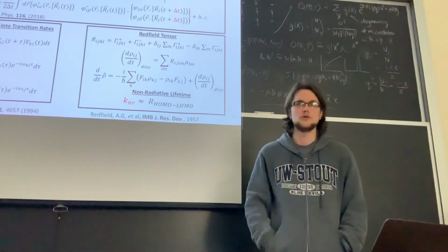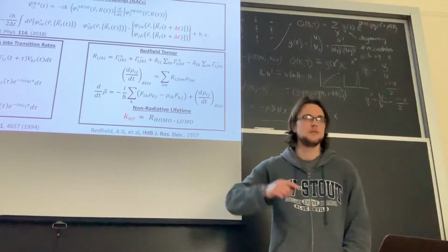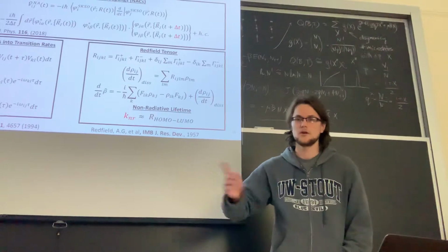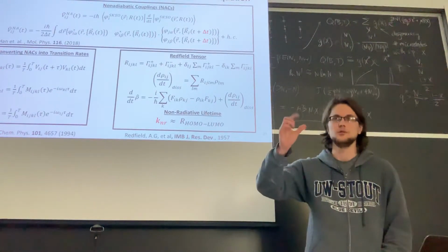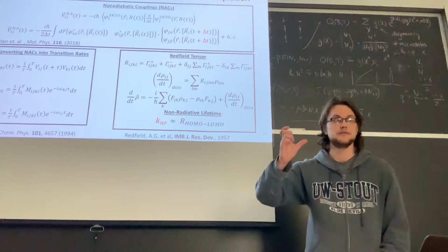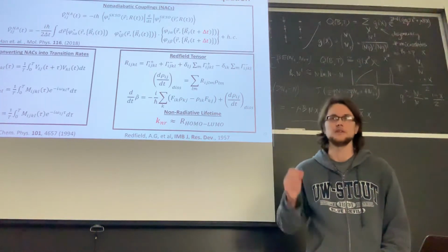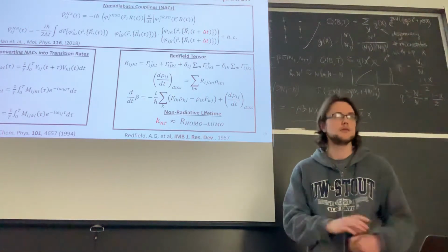Mm-hmm. Okay. And so in the non-polaron picture, we call that slow cooling. But as soon as we change our model into considering polarons, that transition would become the non-radiative recombination. And so we try to utilize that slow cooling as a non-radiative channel for photoluminescence.